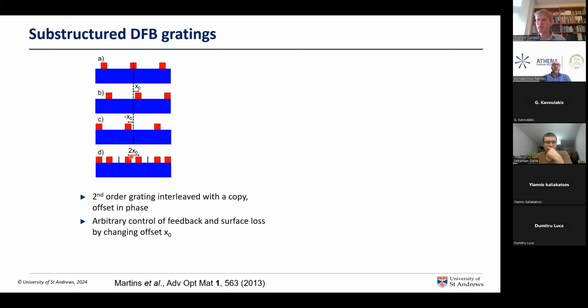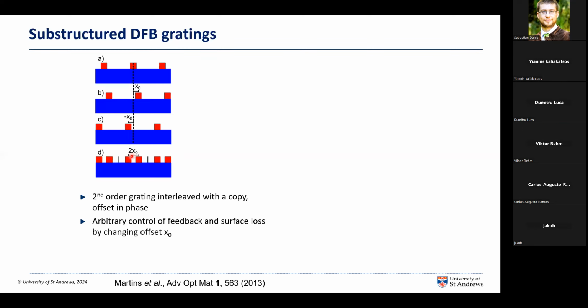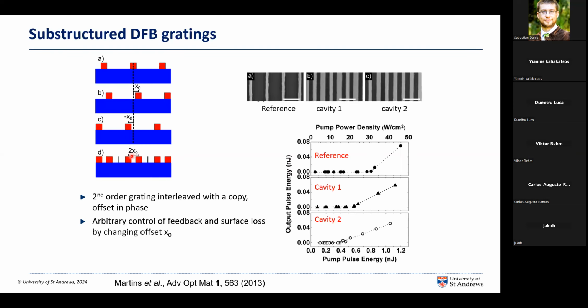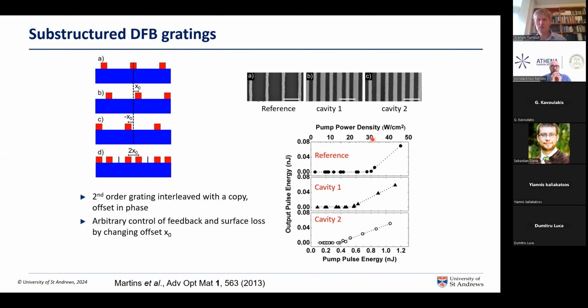And by changing the separation of these teeth within the unit cell, one can actually have huge control over the feedback and the relative amounts of feedback and surface loss in the resonator, which allows us to achieve both efficient output coupling over a large area but keeping thresholds very low. And so this allows us to get down to, again, only a few tens of watts per square centimeter, with a surface emission over a large area, say over a millimeter sort of length scale, which means you can get a collimated beam out from a device that's got very low threshold.